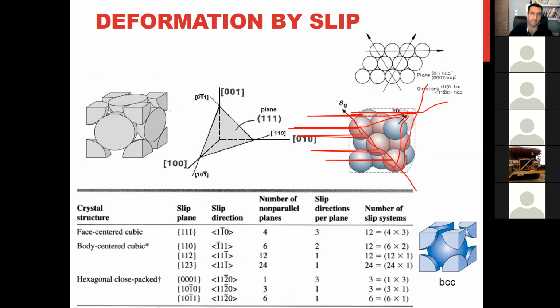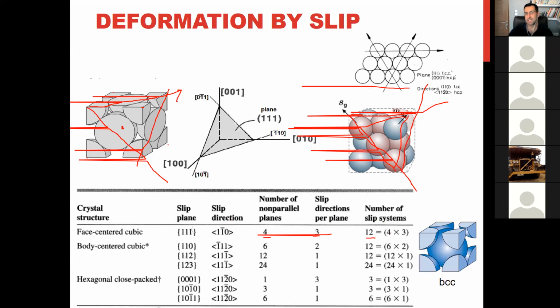It means if you imagine in this cube, this is one, another instead of this corner, we can reach this corner, and this is another, and the other corner on the other side is another, and this is another plane. So we have 4 planes in FCC crystal which have such a close packed configuration, each of which has 3 directions. Here maybe I can draw it more easily. This direction, and this direction. So also we have 3 directions. So the number of slip systems we have in an FCC crystal is 12. Okay, 12 slip systems in FCC crystals.